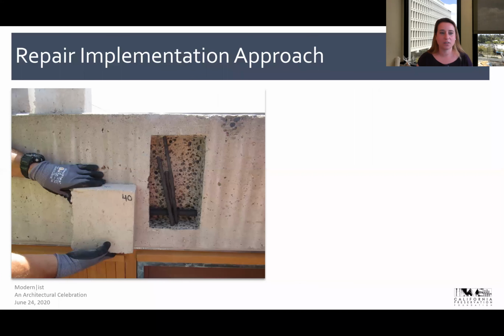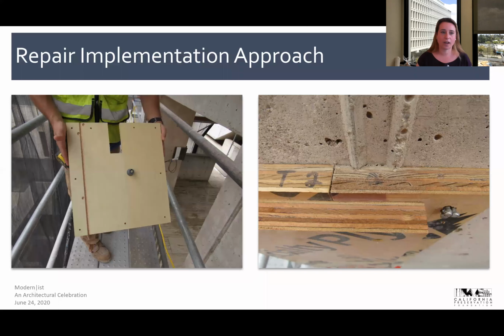Once we'd completed the surface prep, from our palette of 5 colors, the color and the mix design that most likely resembled the adjacent concrete was selected. Custom formwork for that repair area was built. And again, all the details were taken into account. Are there old nail holes from the original formwork, the form tie holes, the fins, the reveals? All of these little details had to be built in perfectly. And then the formwork was installed really tight up